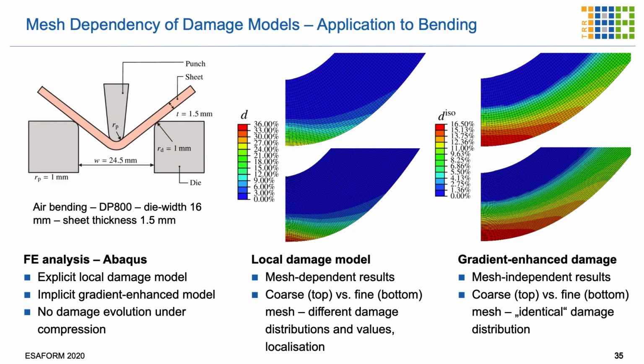So this model is, as I said, a non-local model, and you see here for the bending case the effectiveness of this model. You see on one side a classical damage model. In that case, it was a Lemaitre model, where we have, depending on the mesh size, different damage values. And here you see the gradient enhanced damage model, and on the bottom the fine mesh, on the top the coarse mesh, and you have exactly the same damage distribution for that model.